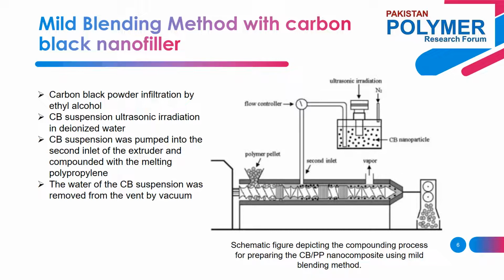An intermeshing co-rotating twin screw extruder was used to prepare the nanocomposite. Polypropylene was put into the extruder and melted at 170 degrees in the kneading block at the end of the feeding section. After that, carbon black suspension was pumped into the second inlet of the extruder and compounded with the melting polypropylene